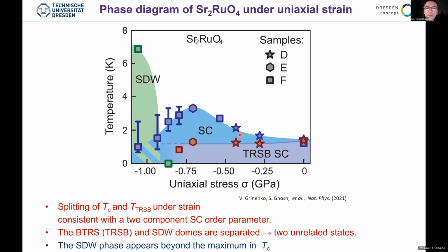If that were true and you calculated in the Landau model, you would have a stronger gradient in the suppression of the time reversal symmetry breaking. But so far, any thermodynamic signal in specific heat is less than 5% of what you have at TC here.